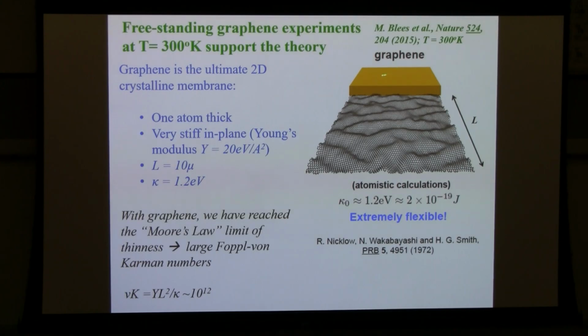The Cornell group uses these gold pads to sort of anchor things and manipulate what's going on. As I said already, for a 10 micron width diving board-like structure with these thermal fluctuations, the Foeppl-von Karman number is 10 to the 12. We've reached, as I said, the Moore's law limit of thinness. We haven't reduced the other dimensions yet, but it's extremely thin. Aspect ratio of 30,000. And if you put in these numbers, as I said, the thermal length is 2 or 3 angstroms.